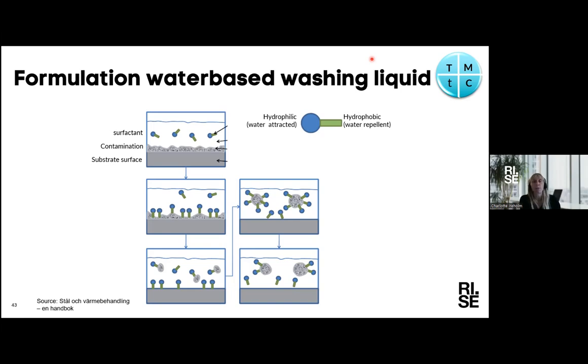And if at least some of the contaminants, or what you want to wash away, are hydrophobic, then the surfactants adhere to that surface, and then with the help of the other parts of the cleaning cycle, for example mechanical action or temperature, the contaminant is covered with surfactants and washed away, so the surface is then clean. If you simplify this a bit, but that's the surfactant part.